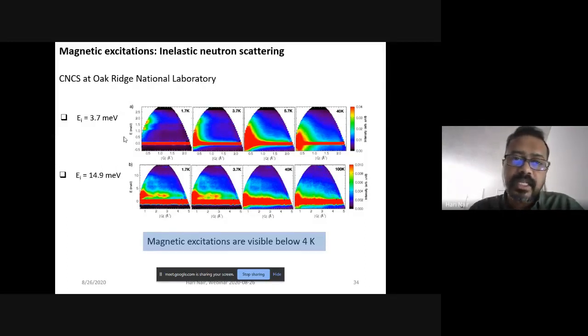So you can see that at 1.7 Kelvin, the high intensity region is somewhere at very low Q and at energies 1 meV or like 1.8 meV or 1.5 meV. As you go to high Q, and remember, Q is nothing but the difference between K and K prime, so it tells you how much momentum is transferred to the sample. At higher momentum, there are no excitations at 1.7K.